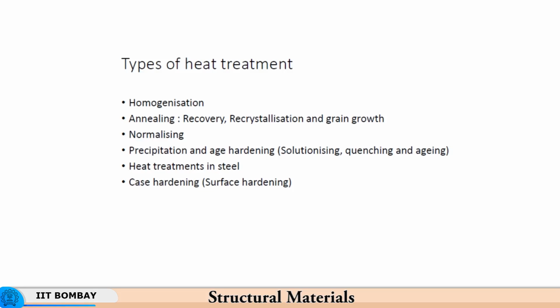We will see now how this happens. If you look at any of the phase diagrams which we have already studied, you will find that as the material cools, the distribution of the alloying elements keeps on changing. So, let us say the material cools from liquid phase to just below the liquidus. Then what you will have is a combination of solid and liquid. Now, the solid which has resulted will not have the same chemical composition as the liquid. So, now the liquid will get either richer or leaner in the solvent, and you will have the